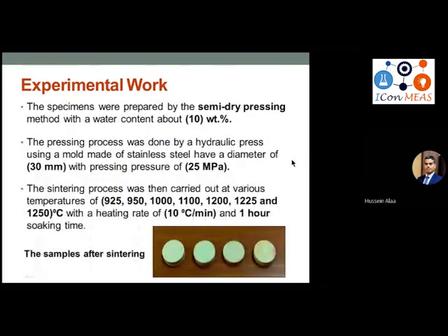The specimens were prepared by the semi-dry pressing method. The water content was about 10 weight percent. The pressing process was done by a hydraulic press using a mold made from stainless steel, with a diameter of 30 millimeters, with a pressing pressure of about 25 megapascal. The sintering process was then carried out at about 7 temperatures ranging from 925 up to 1250 degrees Celsius, with a heating rate of 10 degrees per minute and 1 hour soaking time. This is a sample after the sintering.